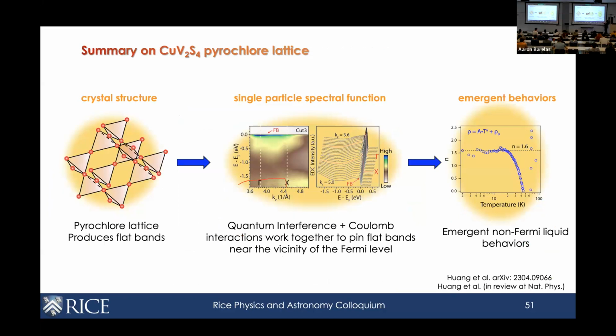There's a prediction on where the flat band should be, and by looking at the single particle spectral function, we can actually see a cooperation of this quantum interference effect plus Coulomb interaction working together to first make the flat band and also bring it to the Fermi level, such that there's a direct consequence potentially in understanding why there's these emergent property behaviors in the transport measurements.